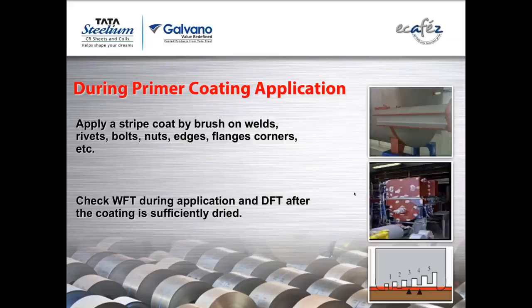Now during primer applications, there's something called stripe coat. You can see in the right hand side pictures 1 and 2. Wherever we have welds or bolts or rivets, nuts, flanges, corners, it becomes very difficult to reach with a spray gun. If I want to reach there, then probably the top areas and other flat areas surrounding get very high DFTs or high thicknesses, which are again not good. So usually it is a good practice to do stripe coat with a brush and then start spraying. So you will get proper even protection in these areas.